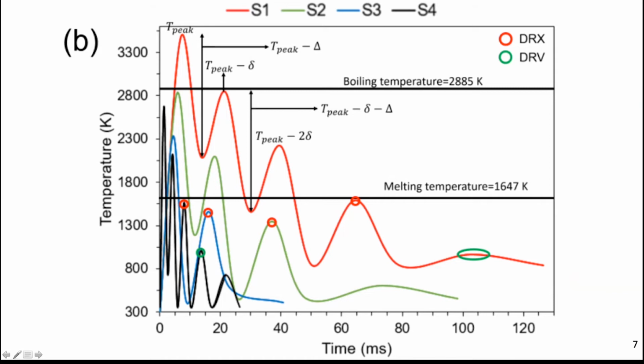So this is the case of 4 samples that we printed. And here you see how when we change printing parameters, we can have very different temperature signatures onto the powder bed. Each of these peaks represents one of the cycles of the different layers that are printed. I don't want to discuss the detail, but I want you to realize first that by very small changes in the scan speed, let's say from 750 millimeters per second to 200 millimeters per second, I can change these patterns that can go from boiling the material literally to just melting it a bit.